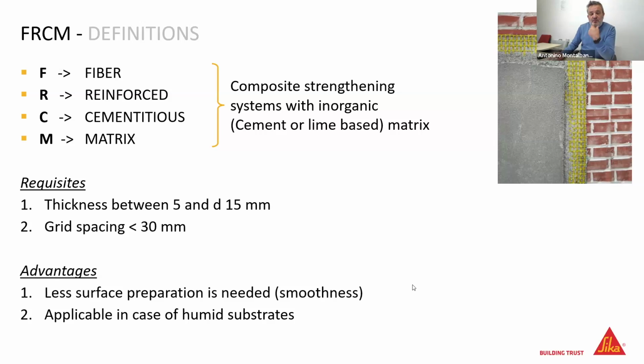And the advantage of these systems is that we need less surface preparation in terms of smoothness of the surface. So we still need to have a clean, dust-free surface. But since we are using a thicker system, we can have a less smooth surface and it will be okay. But one of the main advantages of this system is that, using an inorganic matrix, these systems can be applicable on humid substrates.